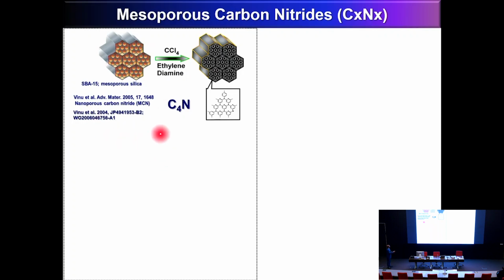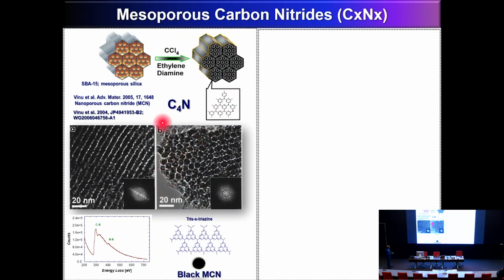In this case, we use carbon tetrachloride and ethylenediamine. At 90 degrees centigrade, it undergoes polymerization and carbonizes at 600 degrees centigrade, and you will get a highly ordered carbon nitride with linear arrays of mesopores, right? And this is electron energy loss spectroscopy. The nitrogen content of the material is very low. It is C₄N and it's not C₃N₄. It's got a pyridinic structure, but C₃N₄ has a triazine structure. Since it has a pyridinic structure with very good conjugation, it is black in color and highly conducting. We call it a conducting carbon nitride material.